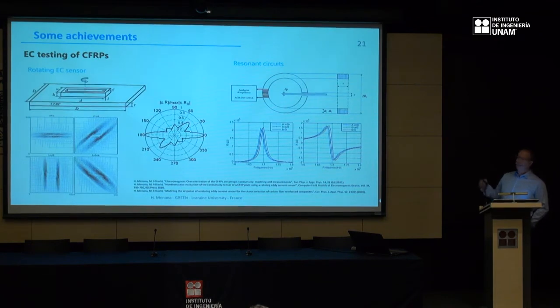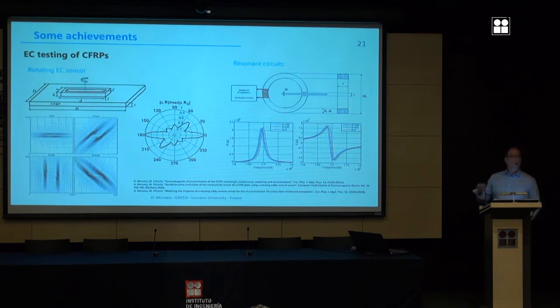Here we have also, based on this numerical modeling, developed rotating eddy current sensors. It's a new configuration of sensor that allows us to characterize the fiber's direction in a multi-ply composite. In this example, we considered a CFRP with plies oriented in the directions 0, 90, minus 90, 45, 90, minus 45, and so on. So you can recognize here the response of the eddy current sensor due to the presence of each ply.